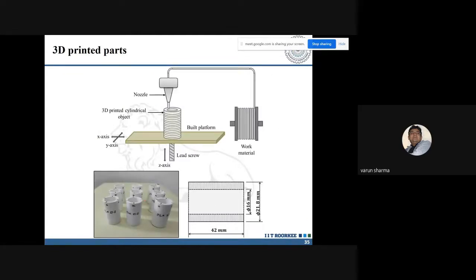For the initial stages, what we did is we fabricated cylindrical specimens, both for the ABS and the PLA. The idea of making this comparative study is that ABS was relatively harder, it was having more rigidity, whereas PLA was relatively a softer material. Now, for the same kind of abrasive media, if I change my workpiece, will my media give me the desired surface finish, will the material removal be the same, or how can we improvise that particular thing.